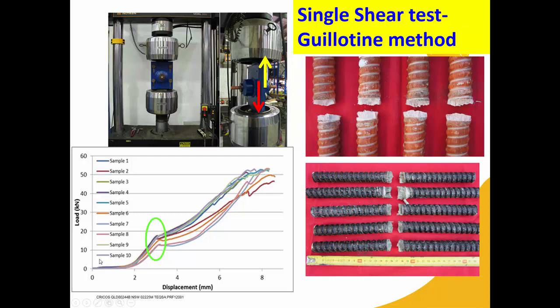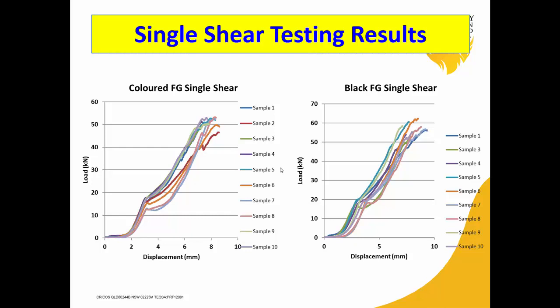This figure shows the shear load on the vertical axis in kilonewton versus shear displacement in millimeter. The peak value is around 5 ton for colored fiberglass. The same test was repeated for black fiberglass, as shown in the right picture, where the left picture shows the colored fiberglass single shear strength. It is concluded that the black fiberglass has shear strength around 1 ton higher than colored fiberglass.